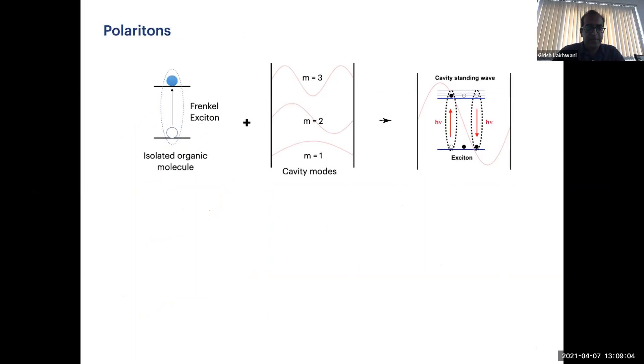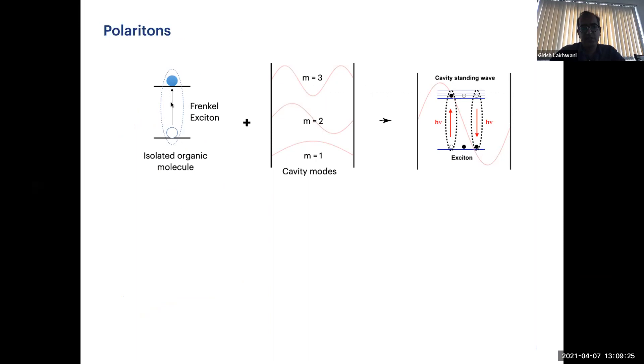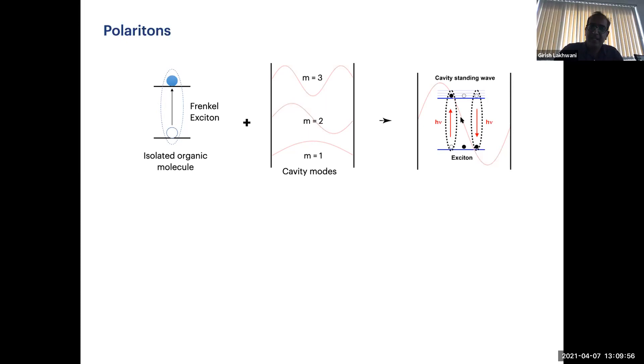If you take a molecule and put it inside the cavity such that the excitation and emission of the Frenkel exciton is in resonance with the wavelength supported inside the cavity, you can see a superposition between a wave, an excitation and emission process. When you shine light at this system, there is an excitation and absorbance process. The emitted light will bounce back from the cavity, get reabsorbed by a molecule — another absorbance event. When it emits again it gets reflected by the cavity, and if these events happen quite fast and numerous molecules support this, you see a superposition of a cavity-supported wave and an exciton absorbance and emission event.